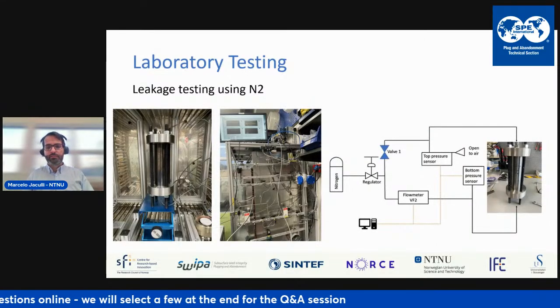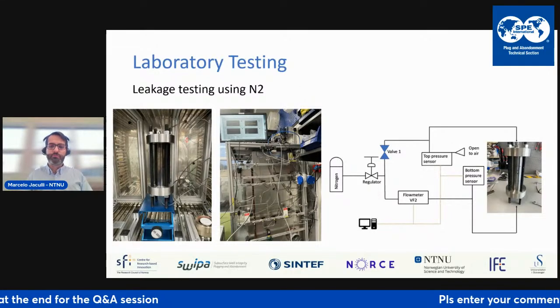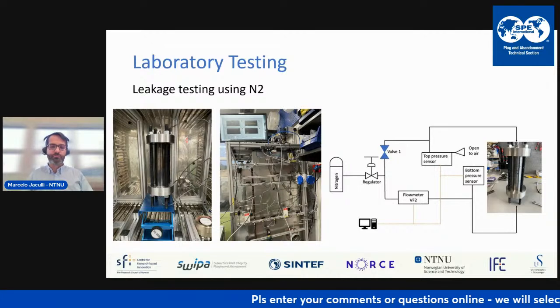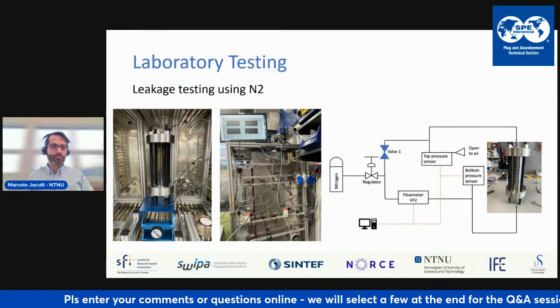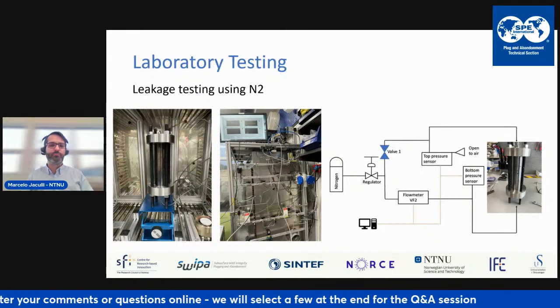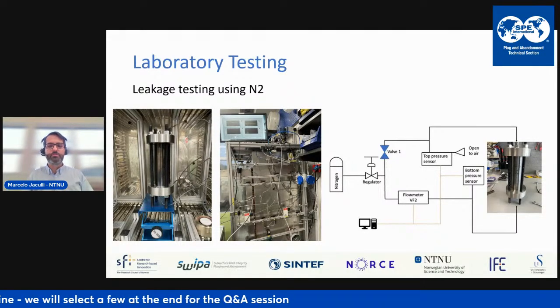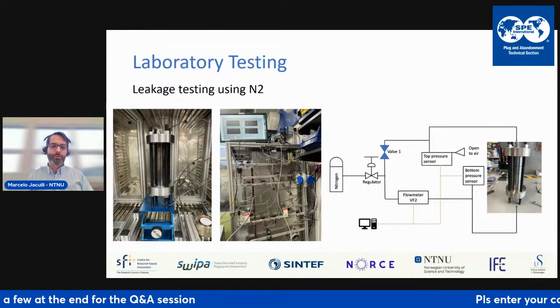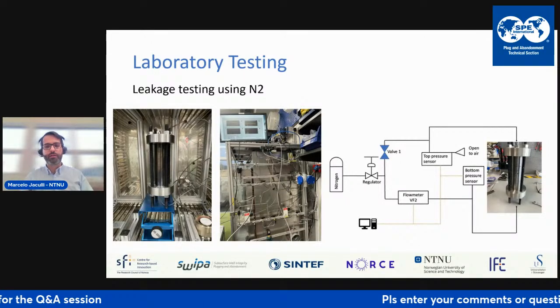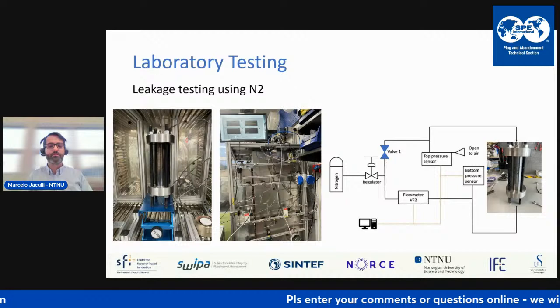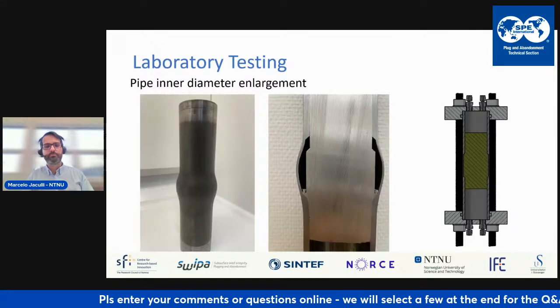Another test we did at the very beginning was testing leakage through it using nitrogen, comparing cement plugs with bismuth plugs to see who had the lesser leakage rates. We saw that bismuth was very competent in shutting down leakage compared to cement, but that was a very early test we did when we were still learning about the whole setup and the whole problem.